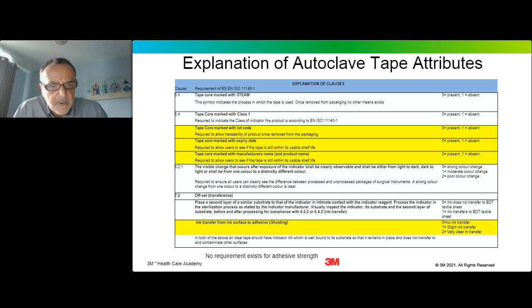Because obviously, if you have a sterilized pack and some of that black ink transfers to another pack, then that is not only unsightly, but it could create some confusion with the end user. Similarly, the ink should not transfer. If you imagine on a roll, the ink surface is in intimate contact with the adhesive surface by the nature of the fact that it's rolled up on a roll. So the ink should not transfer onto the adhesive layer above it, so that you don't then get some weird colour changes occurring when the tape is actually used.